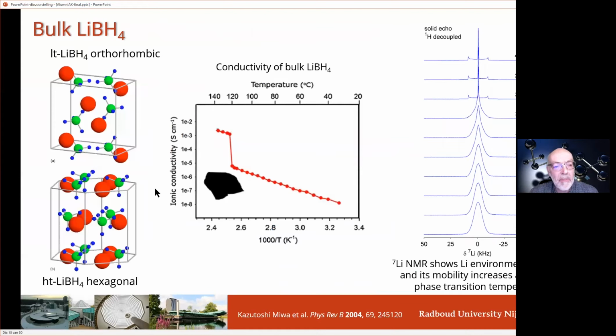One example is a good material that had been identified. Actually, it has been studied for hydrogen storage, but it was found out that lithium borohydride is a material that in the high temperature phase displays a very high conductivity. So this is the room temperature phase. It's an orthorhombic structure. The red are the lithiums, and then we have BH4 groups, nicely in a crystal.